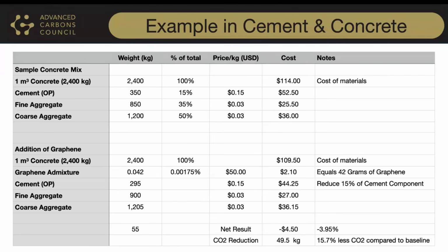15% is quite illustrative. And then you have your fine aggregates and you have your coarse aggregates in a concrete mix. You see them there as a percent of the total at 15, 35, and 50%. And the price per kilo, all of these materials are incredibly inexpensive because they are mass produced and commodity price driven. So cement is about 15 cents per kilo, where the aggregates are at 3 US cents per kilo. So on the fourth column over under cost, you have your cost of materials. So for a cubic meter of concrete, the actual cost of materials, this isn't the retail value that it'd be from a ready mix company to sell, but the cost of ingredients calculates at $114 for 2.5 tons. So an extremely inexpensive, cost-sensitive material.